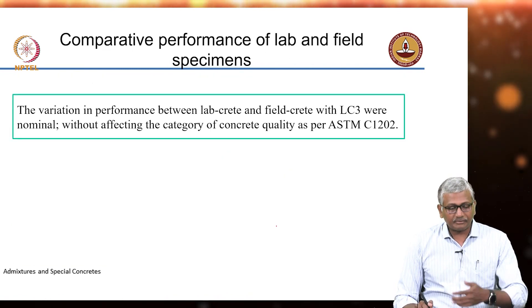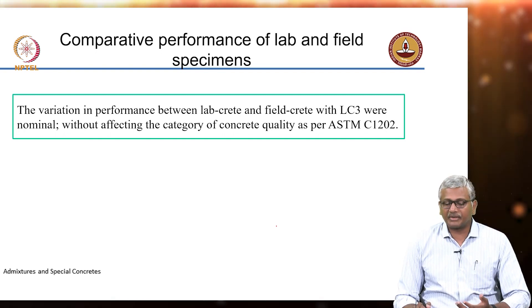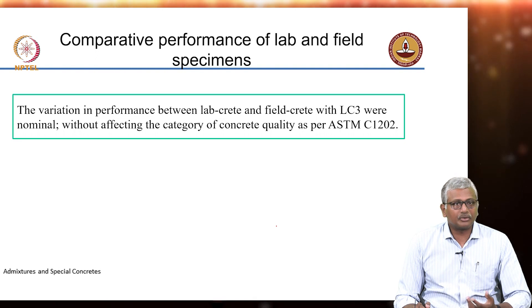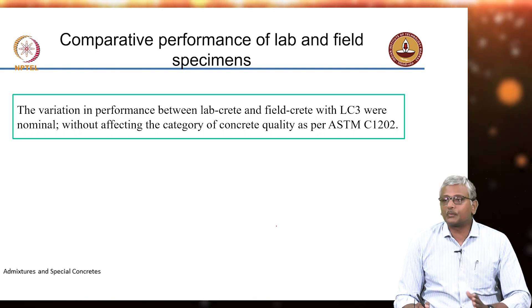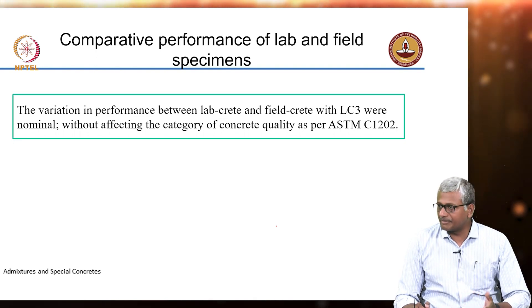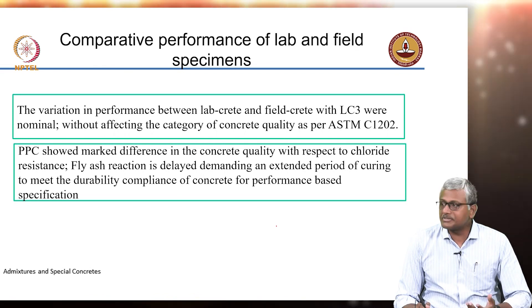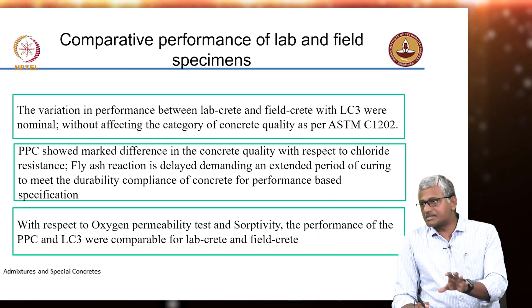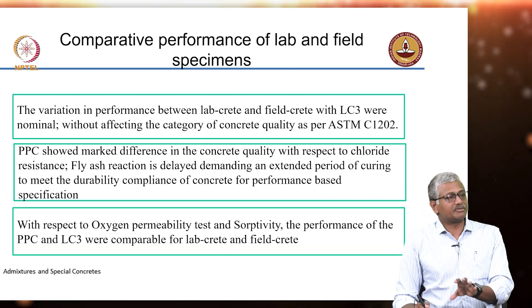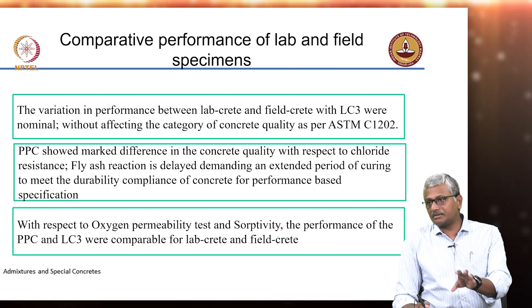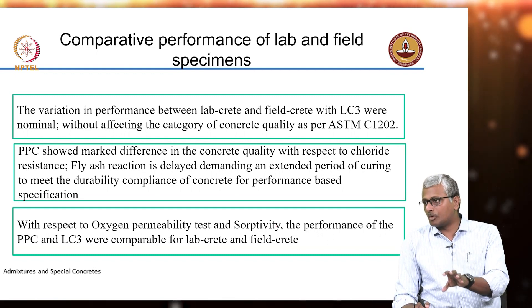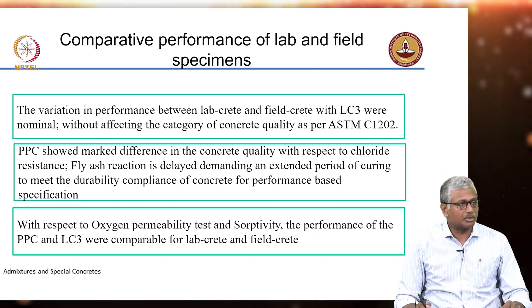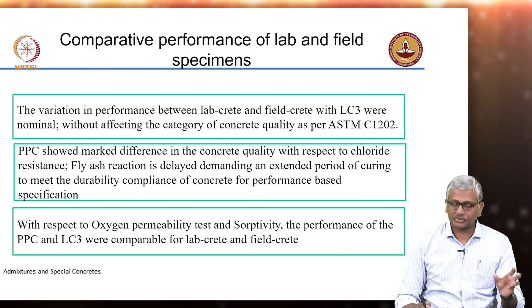The variation between lab-cured and field-cured LC3 concrete was nominal, while PPC clearly shows the negative effects of insufficient curing. All these factors need to be considered when designing the curing strategy in the field — it is not just about strength considerations. You also need to ensure durability is achieved to the level required for protecting the structure in the long run.